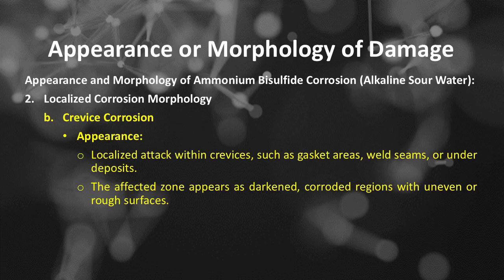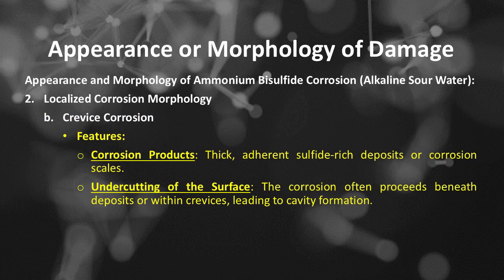Number B of the localized corrosion morphology is crevice corrosion. The appearance of crevice corrosion includes localized attack within crevices, such as gasket areas, weld seams, or under deposits. The affected zone appears as darkened, corroded regions with uneven or rough surfaces. The features of crevice corrosion include corrosion products, thick, adherent sulfide-rich deposits or corrosion scales, and undercutting of the surface. The corrosion often proceeds beneath deposits or within crevices, leading to cavity formation.